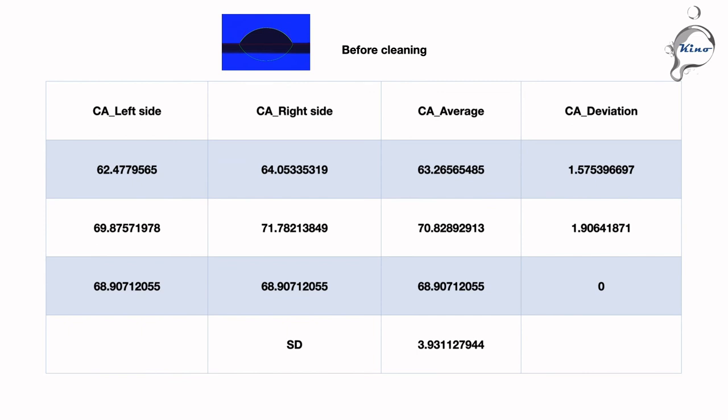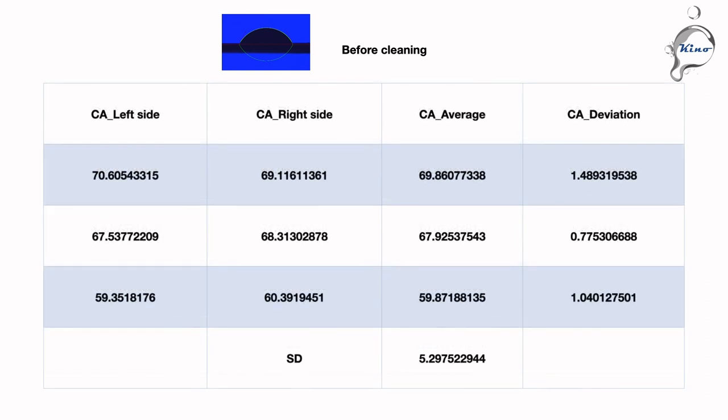These are the contact angle results of milk on sample 19528. These are the contact angle results of milk on sample 19110. The contact angle values of milk of the milk packaging boxes are obviously small, and the maximum contact angle of the two samples is only 70 degrees. Therefore, the wettability compliance of milk packaging boxes should be subject to the contact angle values of milk.